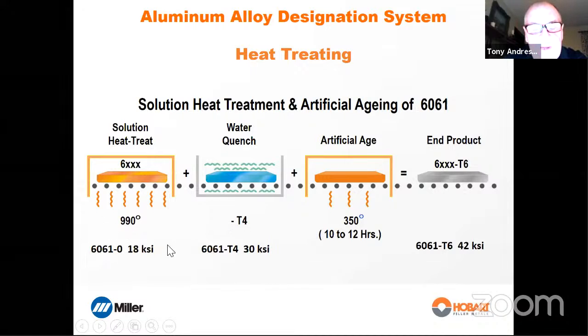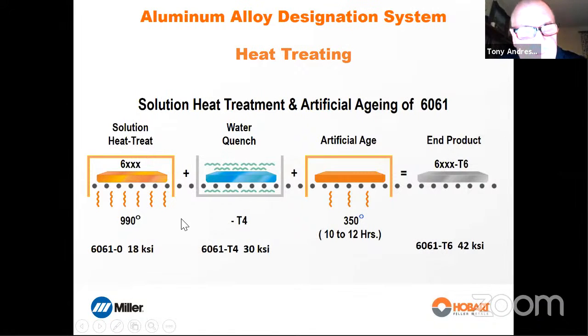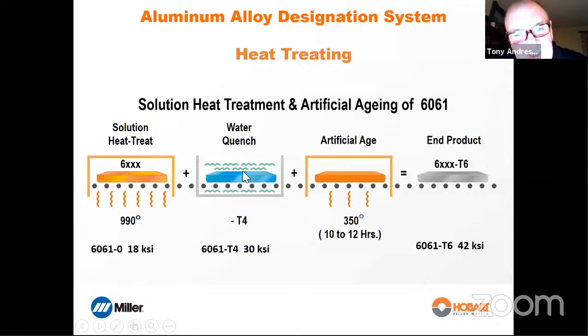You know, what's that all about? Well, this material has small amounts of magnesium and silicon. When we heat this material to these temperatures, the magnesium and the silicon combine and form a compound called magnesium silicide, which is taken into solution at this temperature. When we quench it, we trap it in solution, right, which gives it strength. Now, is this the best strength, and are the mechanical properties great in this condition?